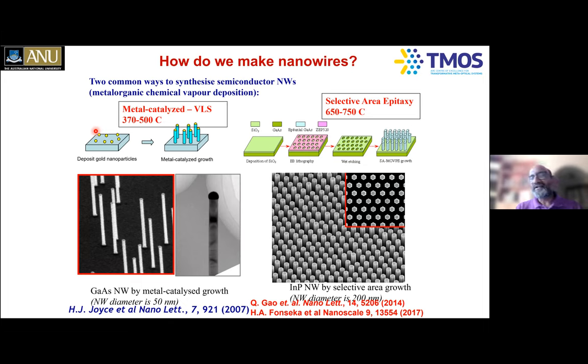And gold has got a melting temperature of more than 1,000 degrees Celsius. But once the gold starts reacting with the gallium or aluminum or indium, then the alloy liquid of gold-gallium or gold-aluminum or gold-indium has got a melting temperature as small as 350 degrees Celsius. We call it a eutectic liquid. Then you put this in a MOCVD reactor, metal organic chemical vapor deposition reactor, and heat it up to somewhere between 370 to 500 degrees Celsius.